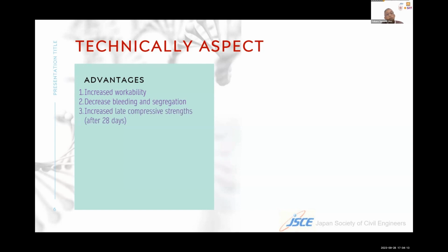The third, increased late compressive strength. So fly ash causes low initial compressive strength in concrete up to 28 days. But after 28 days, the increase in compressive strength continues until more than 120 days.